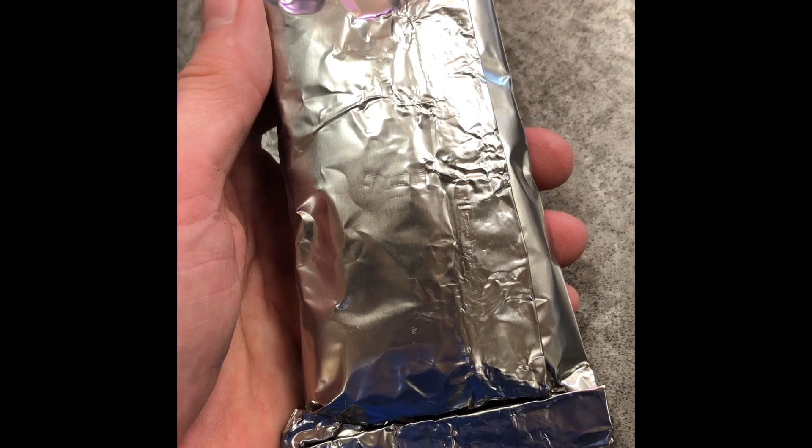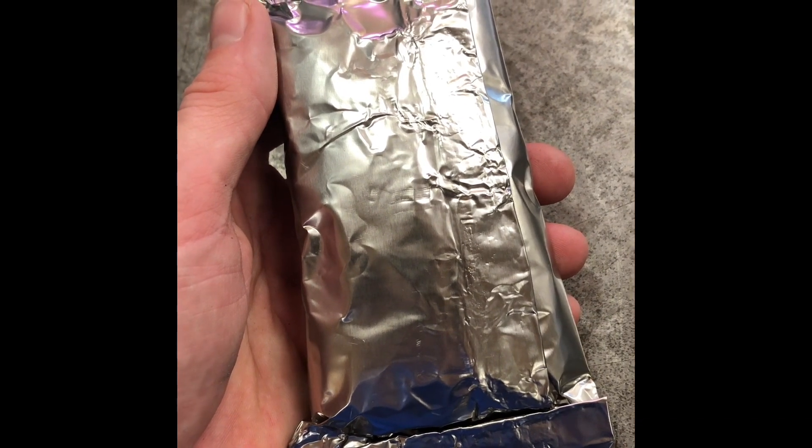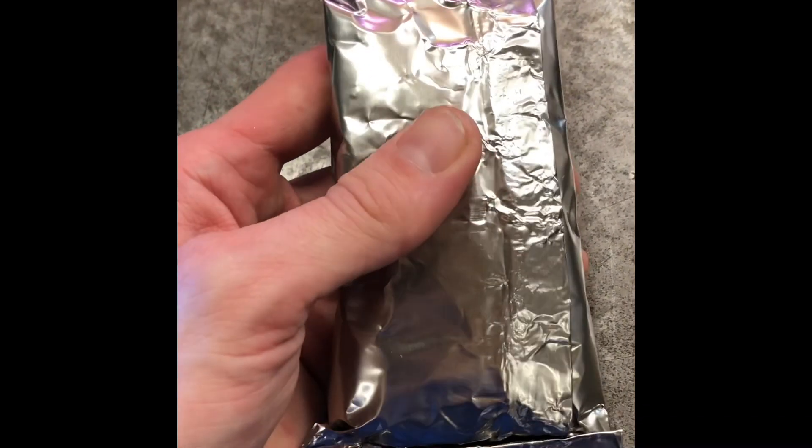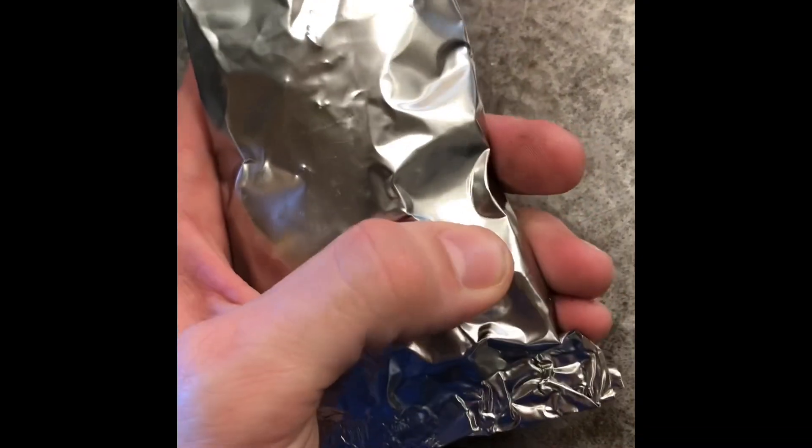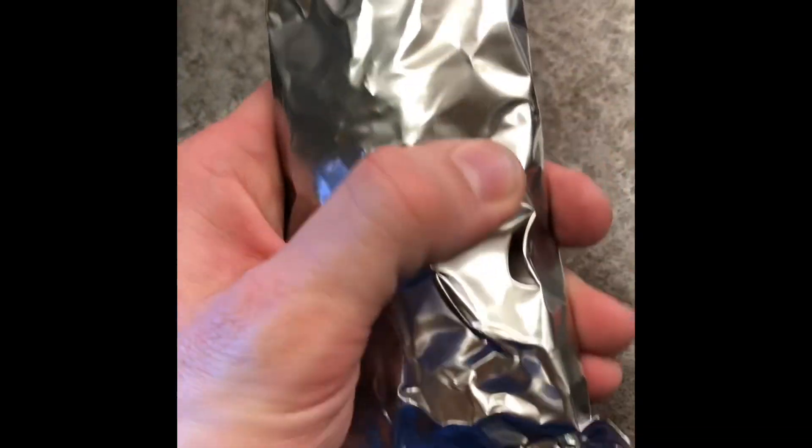I also put in a brown paper bag from your local grocery store, because that brown paper bag will oxidize and burn any oxygen which prevents scale.